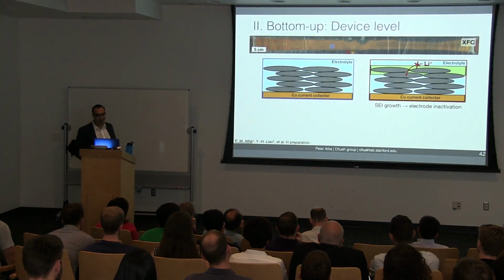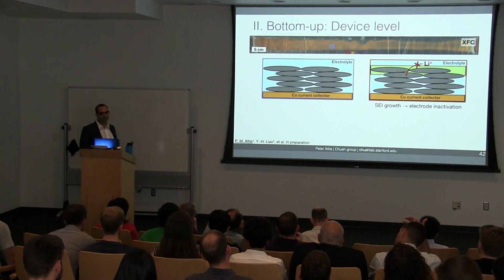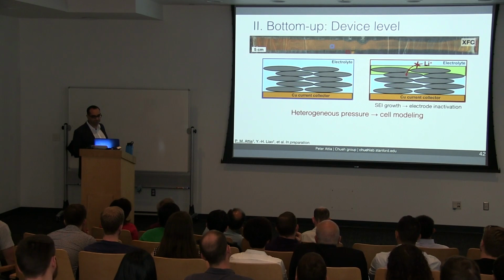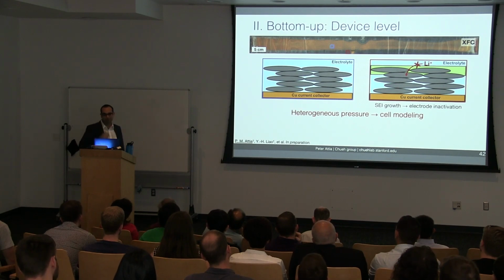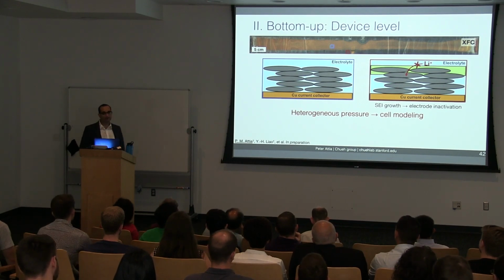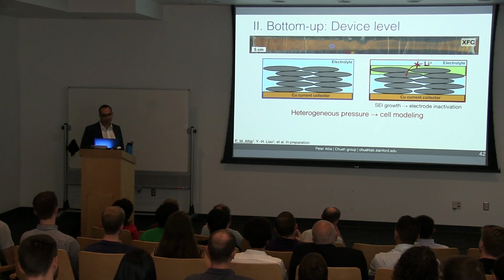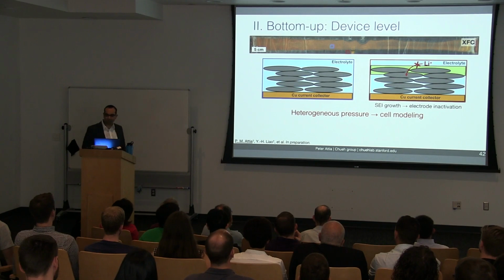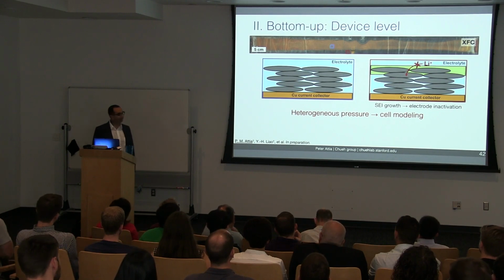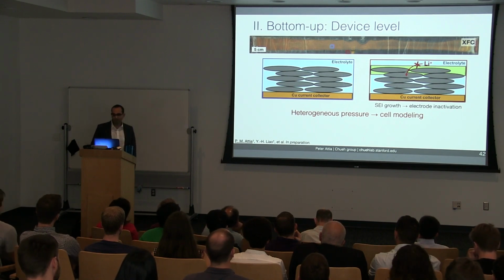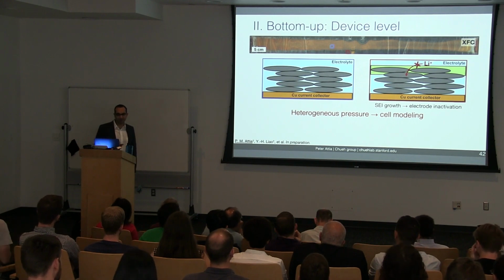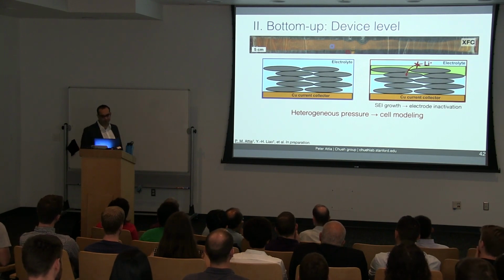So in this section, we saw how SEI growth leads to widespread electrode inactivation during fast charging. For me, there are really 3 big takeaways from this. First is the importance of pressure. Battery models today exhaustively model things like temperature and cell concentration and lithium ion concentration. And most of them don't account for pressure at all. But here we see how heterogeneous pressure leads to significant degradation. So what we really need to do is to start to incorporate pressure into cell-level battery models. Then we can add in heterogeneous pressure, and then we can add in heterogeneous degradation.